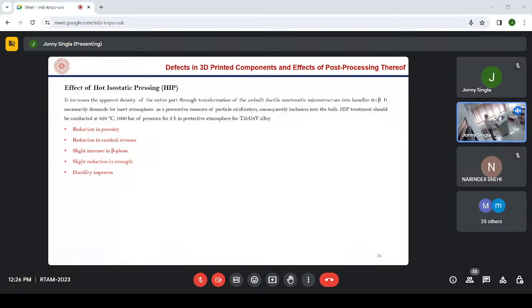Next is the effect of hot isostatic pressing. Along with heat treatment, you also apply a high pressure. This is called hot isostatic pressing. At a temperature of roughly 920 degrees Celsius, you apply a pressure of 1000 bar for 2 hours in a protective atmosphere, so that no oxidation takes place. Because in case of titanium alloy and nickel alloy specifically, there is a possibility of oxidation. To avoid that oxidation, we use a protective environment.